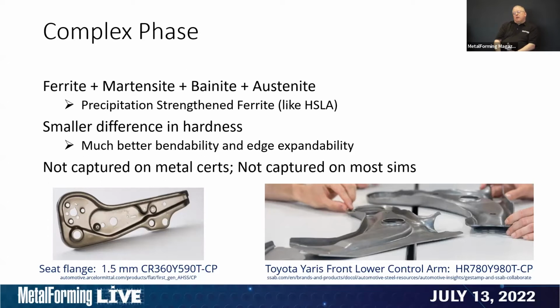The unfortunate, I guess, characteristic with that is the typical test used to characterize the metal's ability for cut edge expansion is known as the hole expansion test. And that test rarely winds up on metal certs. On top of that, the mechanism for cut edge expansion in a production environment is much more challenging. And there's only a select few simulation packages that can incorporate that information. And as I just said, it's really difficult to capture all of the potential variables. So the ability to simulate cut edges, or the expansion of cut edges, is much, much more challenging.